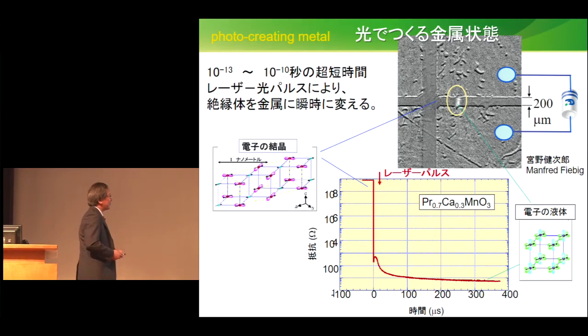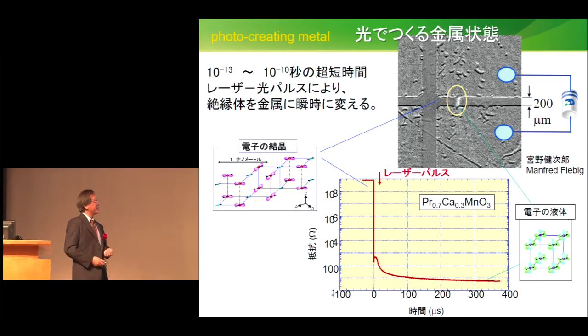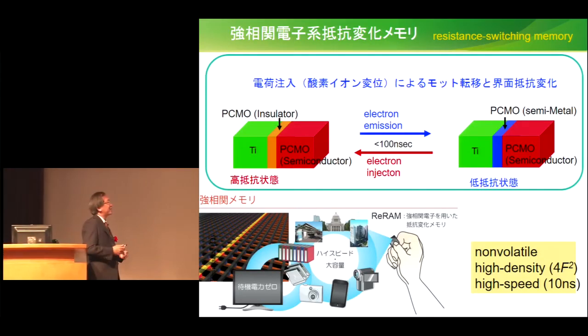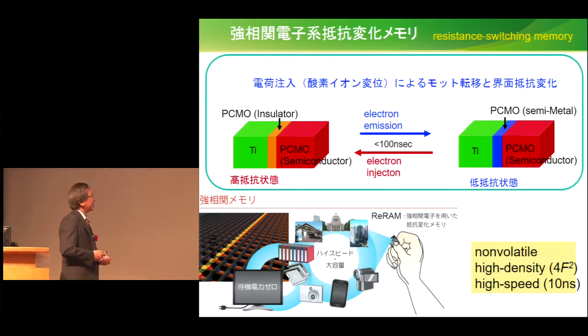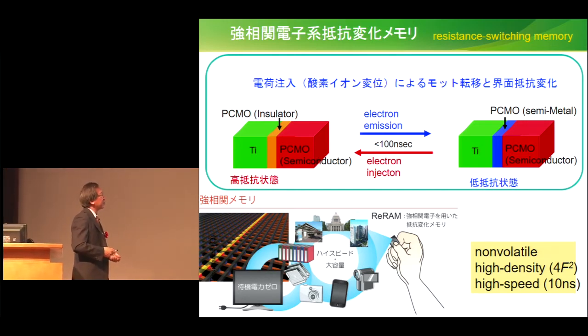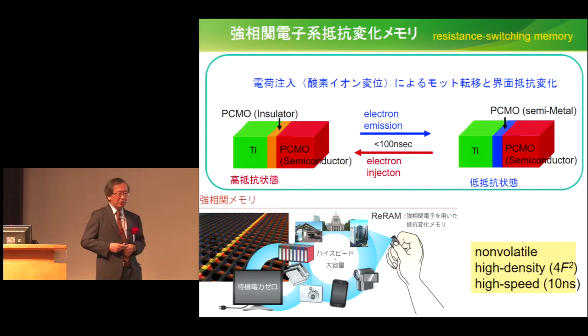Then the color changes. So with a laser pulse, giga-ohm level resistance goes down to the metal level resistance. And that can be maintained as long as you have the applied voltage. Light creates metal. And this metal state accompanies magnetism. For insulator and metal, the transformation does not require changes of the whole device. By the injection of charges, there is an oxygen ion transformation. So you can change the level of resistance because there is a Mott transition at the interface.